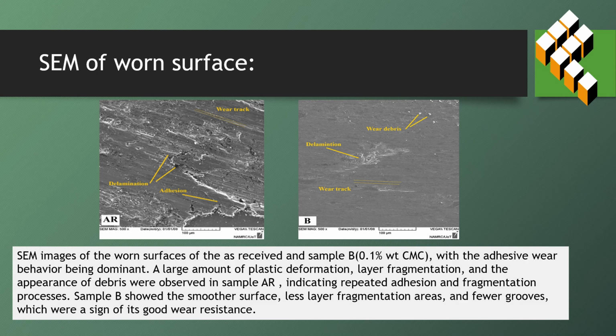A large amount of plastic deformation, layer fragmentation, and the appearance of debris were observed in sample AR, indicating repeated adhesion and fragmentation processes. Sample B showed a smoother surface, less layer fragmentation areas, and fewer grooves, which were a sign of its good wear resistance.